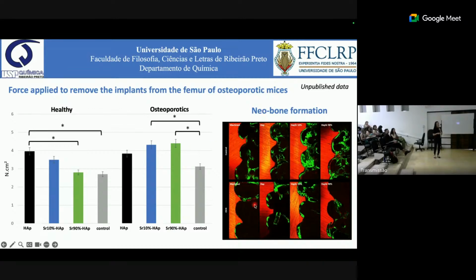And we have lots of results, but I selected this result as an important one. The coated surfaces needed a higher force, reverse torque, to be removed from the bones of osteoporotic mice compared to the control, that is the uncoated titanium. And if we see here the effect of strontium, we had 90% calcium at the surface of the implants, and 10% strontium. With strontium, the implants were better attached at the surface. And the effect of strontium was more important in osteoporotic than in healthy mice.